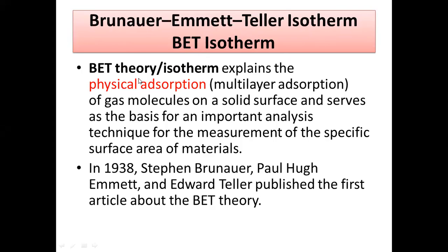And this explains physical adsorption, particularly multi-layer adsorption. We have discussed before in the Langmuir adsorption isotherm the monolayer adsorption, and this is the multi-layer adsorption. So BET is talking about the multi-layer adsorption of gas molecules on a solid surface and serves as the basis for an important analysis technique for the measurement of the specific surface area of materials.